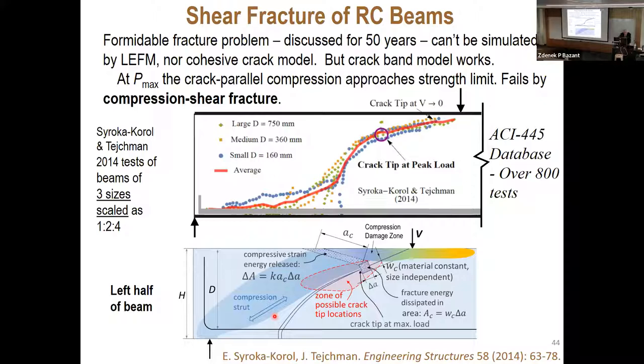Now I'm coming to a fracture problem, which I consider the most difficult fracture problem I encountered. Shear fracture of reinforced concrete beams. This shows the left half of a beam, end support, load, and there is a bar which is anchored, a steel bar, which prevents slip. And we know it fails by cracks like shown here. Now, this problem has been debated for 100 years in the literature and for 40 years by fracture mechanics. Nobody could fit it by cohesive crack model or linear elastic fracture mechanics, but crack band model could.